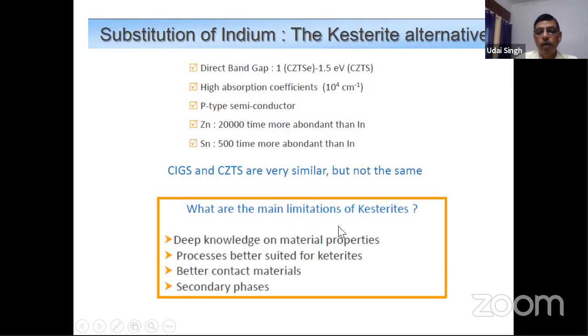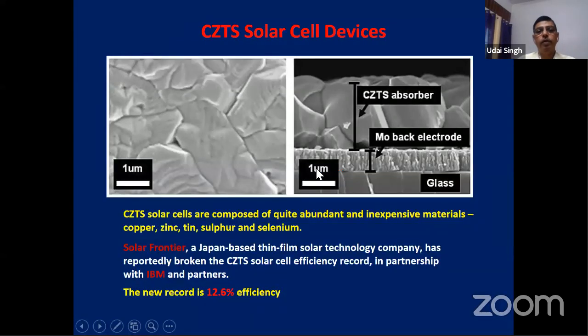So what are the limitations for this? One has to have a deep knowledge because a lot of research has to be done: processes better suited for kesterites, better contact materials. And then the only problem is that different secondary phases are formed in this material. Structure wise, again, it's the same. You deposit the glass, then you have the back contact, then the absorber layer, and on top of this you again have the cadmium sulfide.